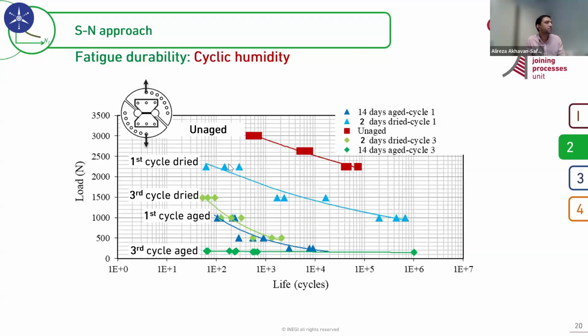Okay. So the reduction in the SN curve that you see here is mainly due to the aging. It means that in case you have more aging cycles, the rate of degradation will be higher, and you will have a bigger drop in the SN curve. Yeah, that's clear now. Thank you.